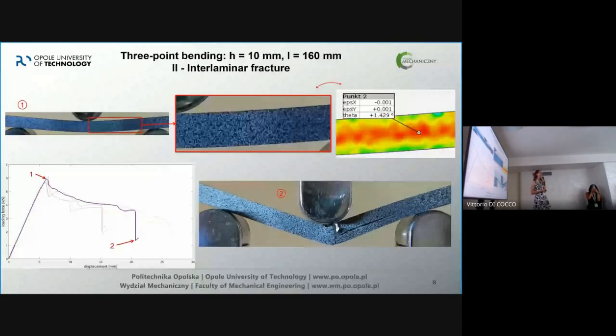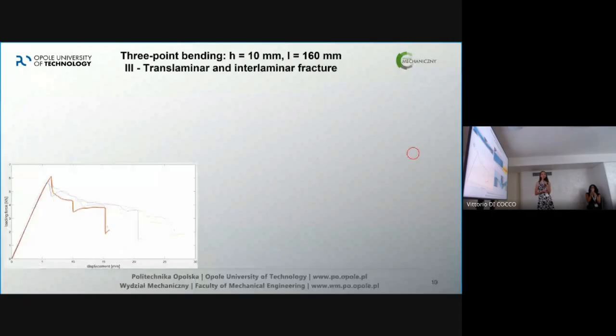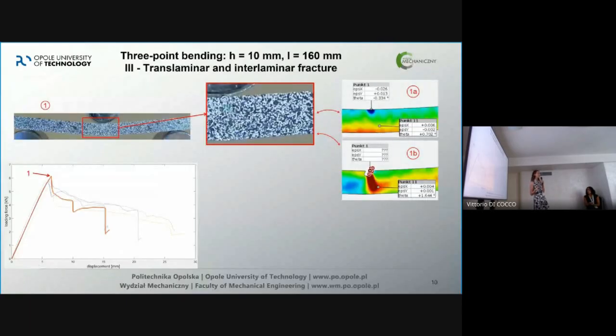my material. And another one was even more interesting because I had both translaminar and interlaminar fracture, and they happened within milliseconds of each other. Here, we have a very big epsilon x coming from compression. And here we have buckling of the fibers. And at the same time here, I started to have lamination. So milliseconds between each other, I had 2 different types of fracture.